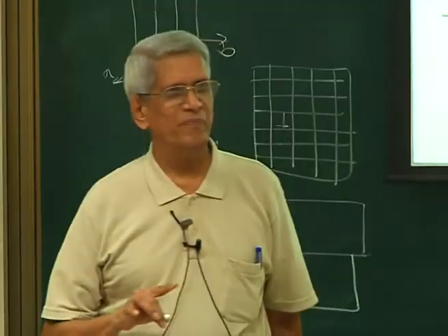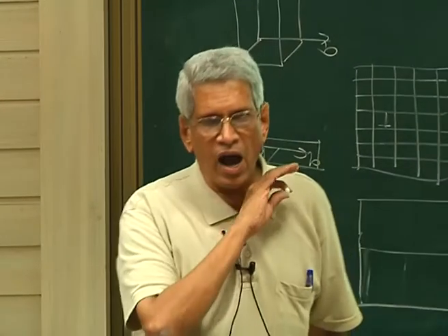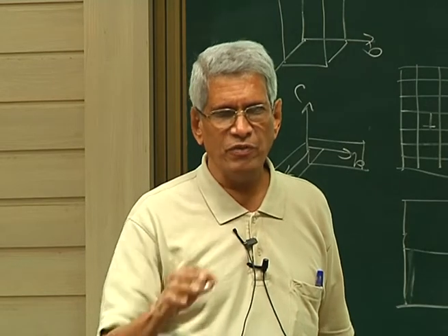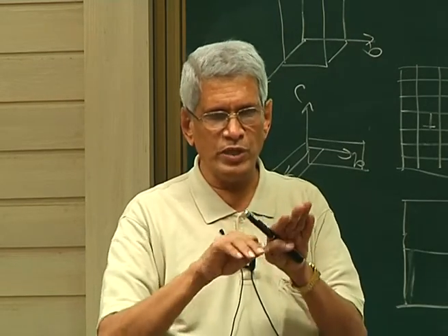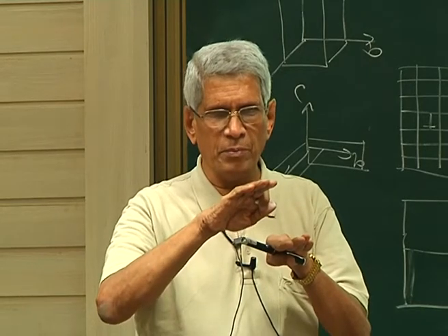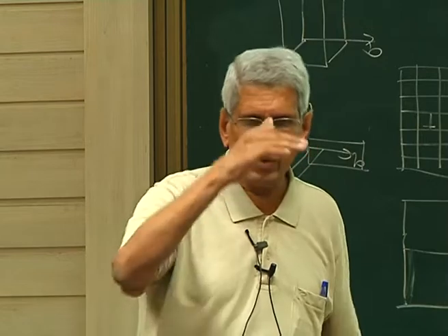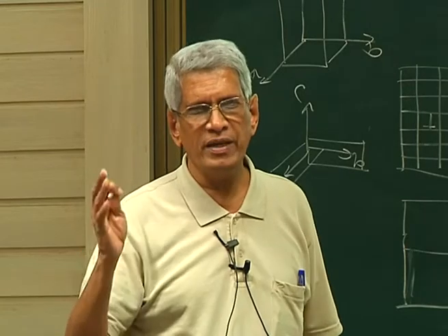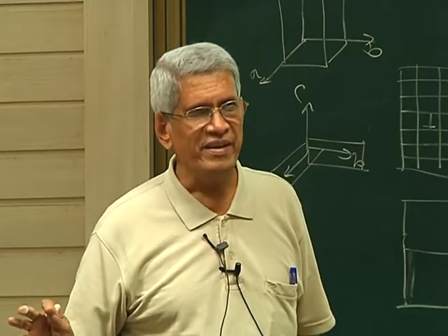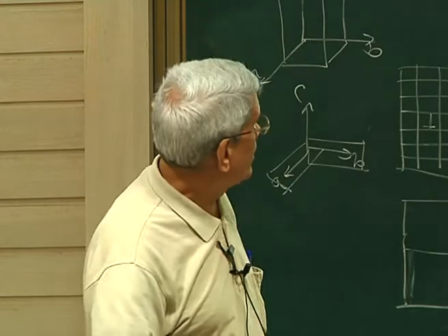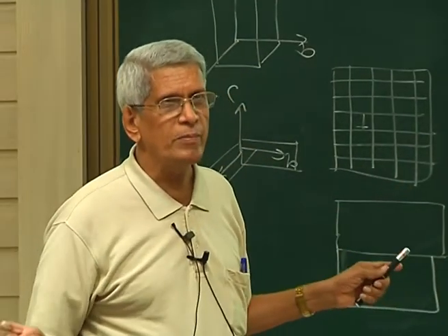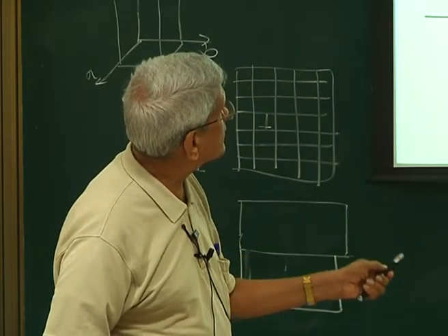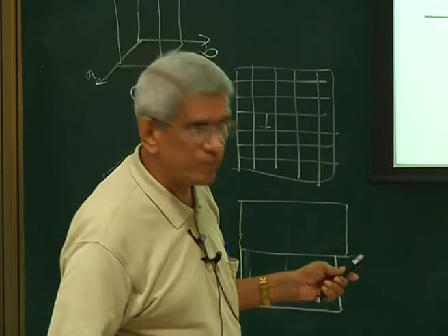That defect could appear as an ordered variant that creates a domain boundary, or it can come as an antiphase boundary. If it is just one antiphase boundary, it only shifts the crystal structure from one to the other but with the same orientation. If they happen over a sequence of layers, that may in fact rotate the crystal structure. Then we say that it's a domain or an ordered variant. You understand that? That is how these variants come. So this is how twins are formed in the material. Is it clear? And this plane is essentially called a composition plane or a coherent twin plane.